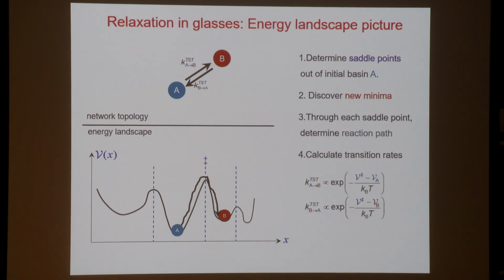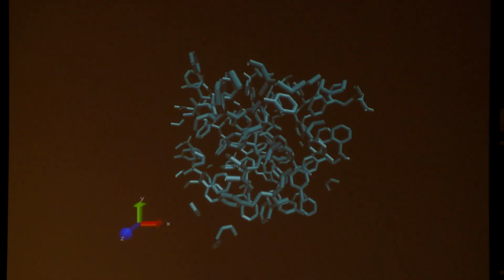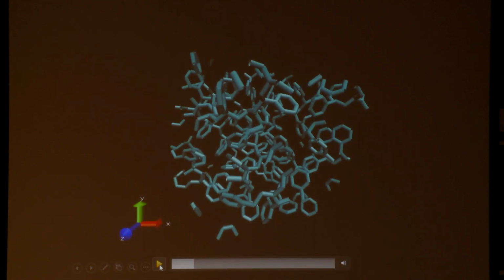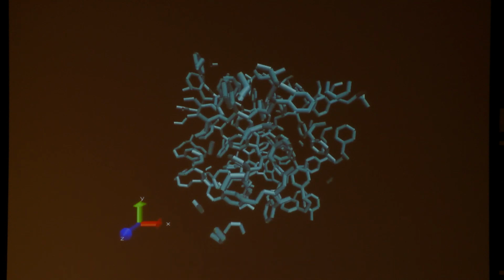This, of course, can be done also for other minima that are connected to the original minimum. So in the end, one can sample a network of connected minima and atomistically calculate the rate constants of these connections. This is an example of such an elementary transition from minimum to minimum. It is atactic polystyrene, a rather simple small system, and we have a transition from the original minimum to a new minimum, which, as you can see, is accompanied by subtle, cooperative motions of the atoms in the system.